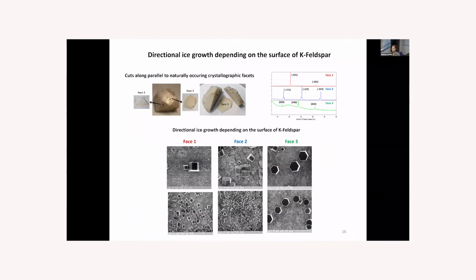We have also studied different minerals in the feldspar group, mostly the potassium feldspar. And here, as an example, you can see one of the minerals which were cut following the naturally occurring facets of feldspar. Here we have three different faces: face 1, 2, and 3, and we have performed the experiments of the ice nucleation and growth at the ICEM. And here you can see that, as in Kiselev's paper, our ice crystals were growing with the preferential orientation of ice, basal plane and prism faces shown in different faces.